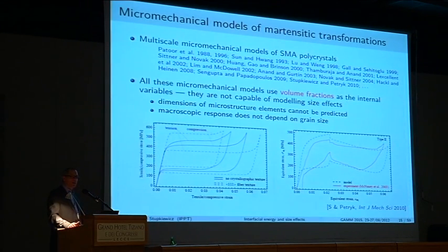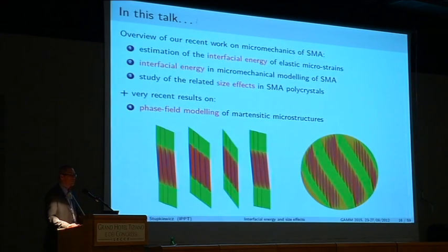Okay. Of course, on the market, there are plenty of multiscale models for shape memory alloys. Here I list some. Just a very small subset of the available micromechanical multiscale models for shape memory alloys. They consider plenty of effects, very important, less important, but what none of them considers are the size effects essentially. Because the traditional way of modeling is to use volume fractions. When you use volume fractions, you don't really consider the dimensions of the microstructure. You don't have the size-dependent contributions in your system. So none of the available models does it, essentially. So our goal is actually to fill that gap.